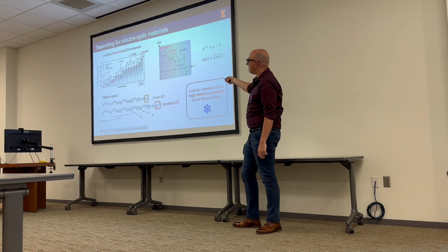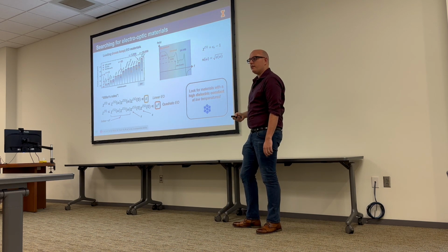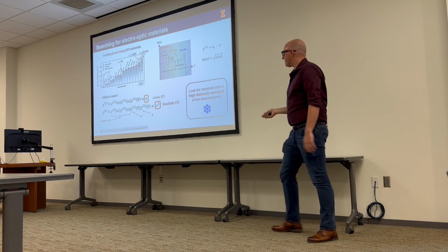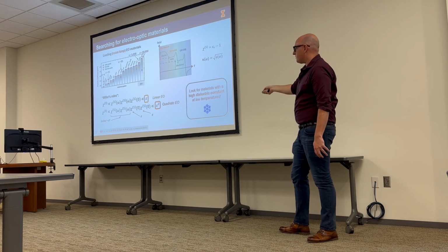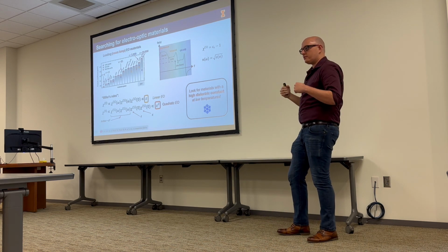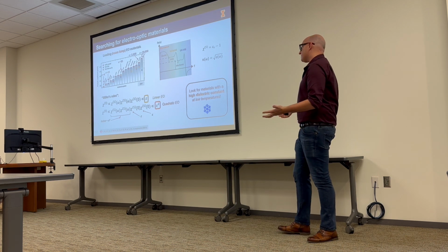The problem with this trend is these materials were all measured at room temperature. And so if you want to do quantum nonlinear optics, you need to find materials with a high dielectric constant at low temperatures. So we've understood the physics, we only want to find high dielectric constants at low temperatures.